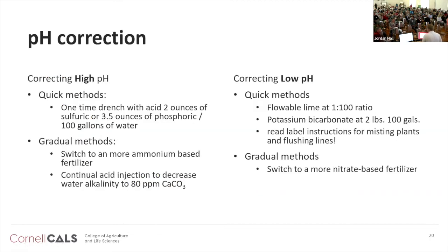So overall methodology for correcting pH: if your pH is testing high, the quick method is to do a one-time drench with acids, either 2 ounces of sulfuric acid or 3.5 ounces of phosphoric acid per 100 gallons of water. A lot of growers will use that through a fertilizer injector that's, say, a 1 to 100 injector. So then their stock solution would be 2 ounces of sulfuric per 1 gallon of stock solution, and then that gets diluted down by the injector to 100 gallons of water. Gradual methods to correct for a high pH are to switch to a more ammonium-based fertilizer, or if you know that your tap water source is high in alkalinity, to continually add a dilute amount of acid to decrease your water alkalinity down to 80 parts per million calcium carbonate.